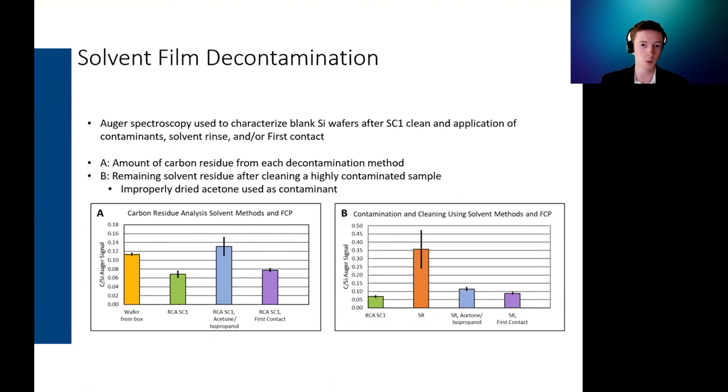That replaces the native oxide layer on the silicon wafer. From there we can apply the solvent method and also First Contact, and you can see the remaining residue after that based off of a clean sample. First Contact leaves a lot less residue than the solvent, but both are around the area of just a freshly clean wafer, so neither are catastrophically bad. But First Contact is distinctly better in this regard.